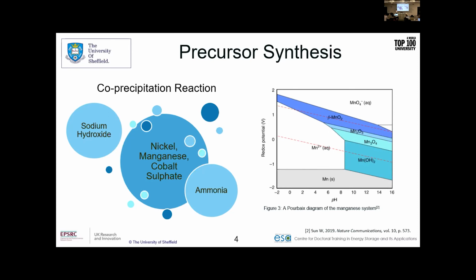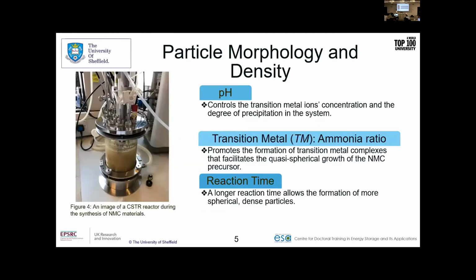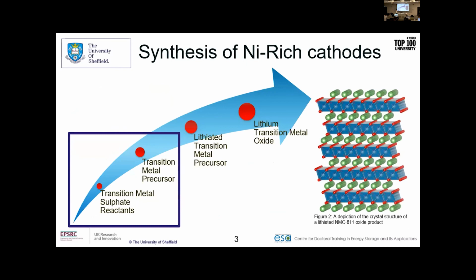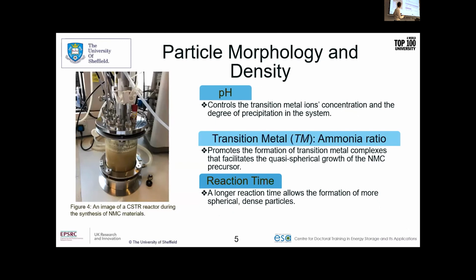If we make it too oxidized, then they'll form these rogue states and have different rogue elements within this structure, which if we look onto the next slide, it will disrupt this, so it won't be as layered. It'll have lots of different blocks, which will cause them to be a bit more zigzagged, and it won't neatly form this nice crystallized structure. So yeah, I was talking about the pH just now, and that helps determine at what rate it precipitates.